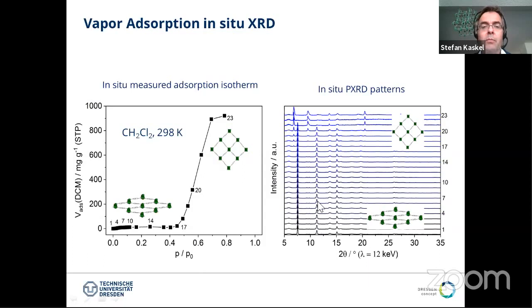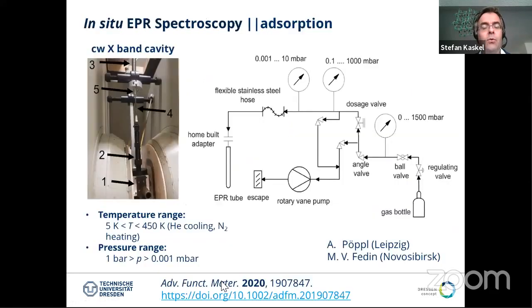And here you see how the powder patterns develop. You can see basically the new OP phase starting to appear here. Here we have a mixture of OP and CP phase, and then the pure OP phase at these higher vapor pressures in P over P0. So this is an enabling technique. You can use diffraction for vapors and gases. And here the speciality is that we can also measure a full isotherm at the same time. So diffraction gives information about the long range order, but not about the local structure or defects or other details.